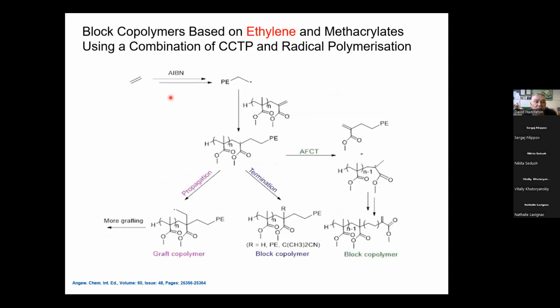So the strategy here is, what Frank does on a daily basis is they'll polymerize ethylene with a free radical process, normally in emulsion, but not exclusively in emulsion. So they'll be doing an emulsion polymerization of ethylene, and then make polyethylene. And then they're very well set up to characterize the polyethylene by high temperature NMR and thermal analysis. So our experiment was we would put in our oligomers, and n would now be maybe 10 or 15 or 20. And what we wanted the polyethylene radical to attack there, which would produce a radical here.